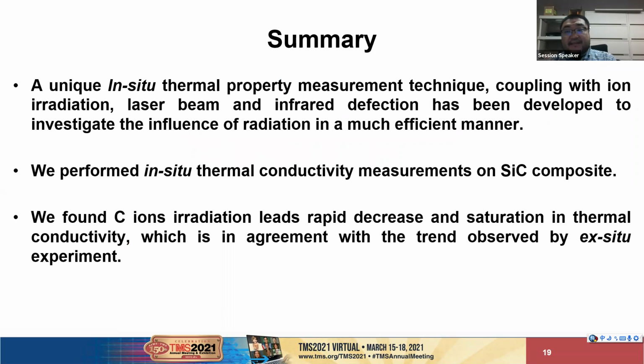Finally, let me summarize my talk. In my presentation, a unique in situ thermal property measurement technique coupling ion irradiation, laser beam, and infrared detection has been developed to investigate the influence of radiation in a much more efficient manner. We performed the in situ thermal conductivity measurement on silicon carbide composite, and we found that the ion irradiation leads to a rapid decrease and the saturation in thermal conductivity, which is in agreement with the trend observed by ex situ experiments.